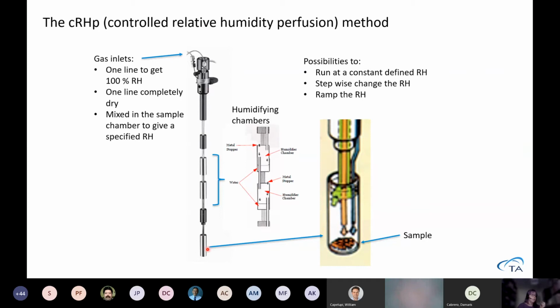So one gas line goes directly into the sample, and one line goes through the humidifying chambers. This chamber sits in the thermostat, so they have the liquid. Now we talk about water and humidity, it could be other solvents as well, but it will have the water, so we will humidify the air at the measuring temperature before it goes into the sample chamber. So we can play with how much gas goes through the dry line to the wet line, and we can create the relative humidity over the sample to determine where I want to measure. So we have the possibility to run at a constant defined RH. We can stepwise change the RH, or we can ramp the RH over the sample.